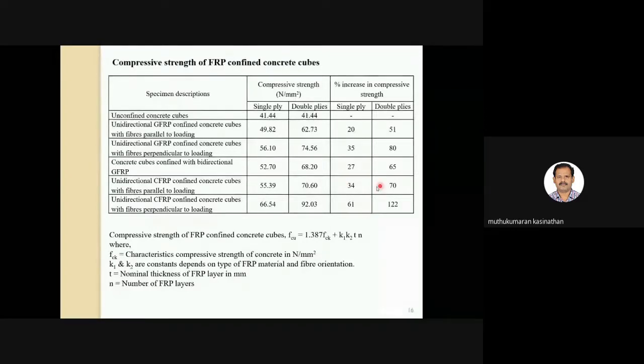And using number of plies, when we increase the number of plies, capacity is also increasing. But overall, if you look at the improvement, the carbon fiber concrete with the perpendicular orientation is giving almost 61% increase over the conventional concrete. But having a small amount of carbon fiber, a single layer, increased minimum 20% over the conventional concrete, and increasing number of layers from single to double, minimum we are getting 50% improvement.